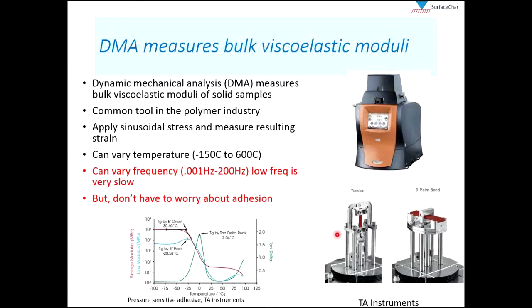Now there are different ways to mount the sample and oscillate it in DMA, and here I just show two examples of the clamps. So our sample is maroon, and here it's being held in tension, and here it's being held in a 3-point bending clamp. The tension configuration is the best analog to the AFM tip-sample interaction, but 3-point bending is very common as well. And here is just some data again from TA Instruments, looking at the various viscoelastic moduli, the storage modulus, loss modulus, and then loss tangent for a pressure sensitive adhesive.